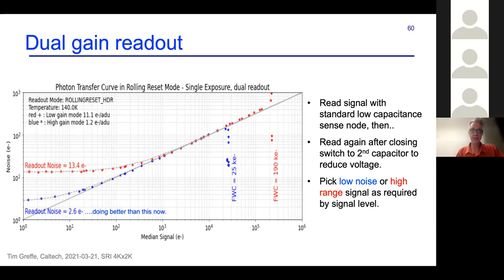But we can actually do this to every pixel, so that we read it first in high gain, switch in the second capacitor, read it again in low gain, and the pixels which are below our high gain well capacity have low read noise, and the pixels that have higher signal, we just choose the low gain setting. So we select between the two readings and pick the one we want. And what this effectively does is it extends our dynamic range up to a well capacity that's more like a CCD. It's about 190,000 electrons on this particular device.